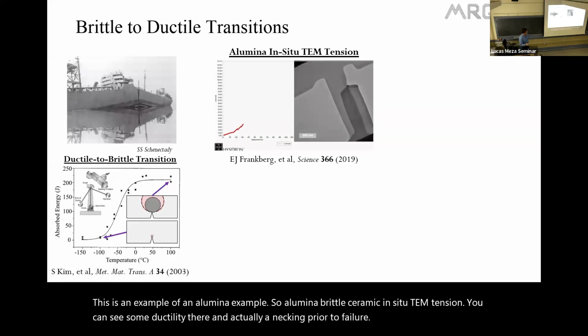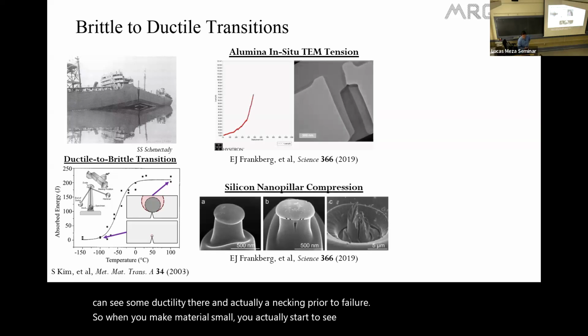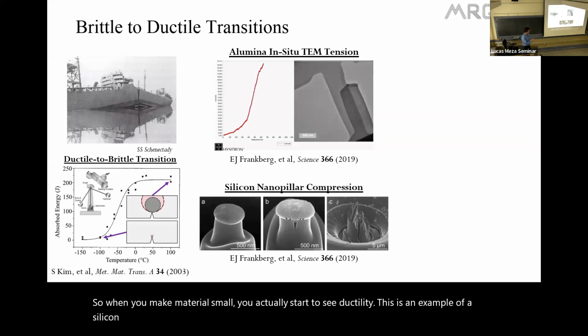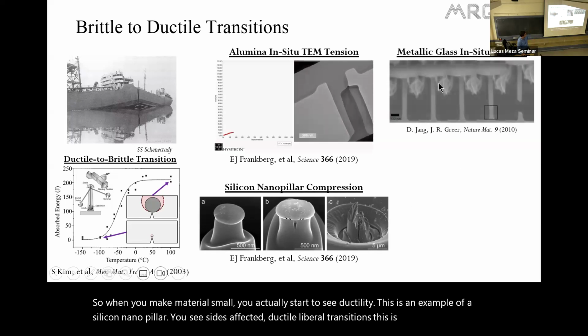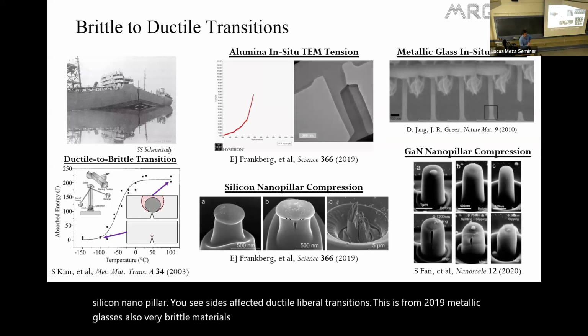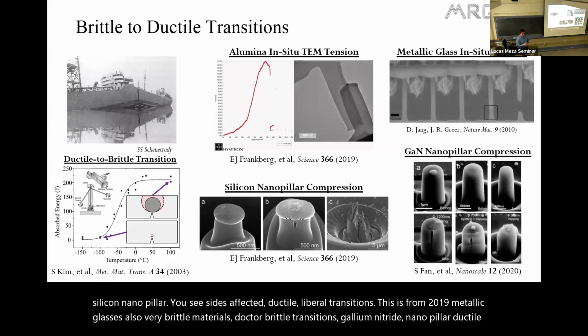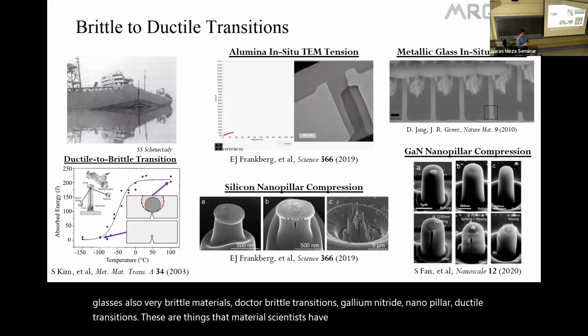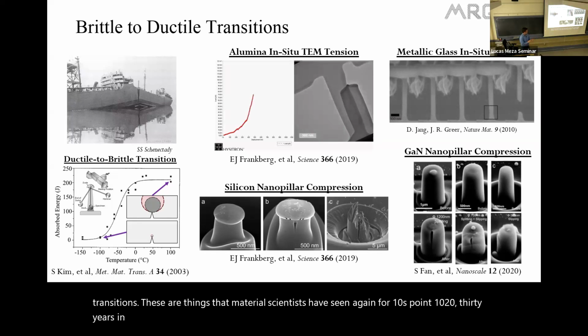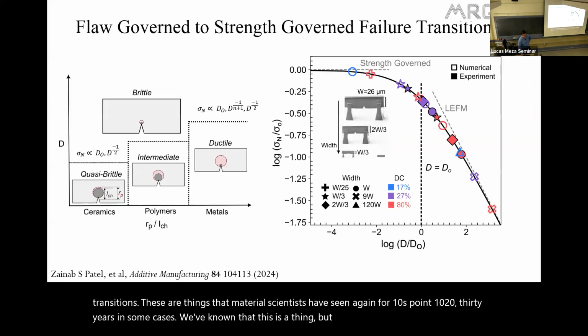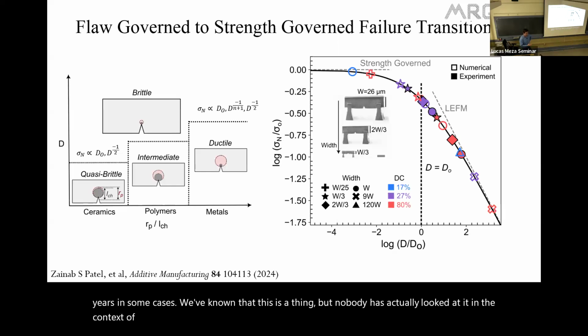So when you make materials small, you actually start to see ductility. This is an example of a silicon nanopillar. You see size-affected ductile to brittle transitions. This is from 2019. Metallic glasses, also very brittle materials, ductile to brittle transitions. Gallium nitride, nanopillar, ductile to brittle transitions. These are things that material scientists have seen, again, for 10, 20, 30 years in some cases. We've known that this is a thing, but nobody has actually looked at it in the context of these fracture size effects.